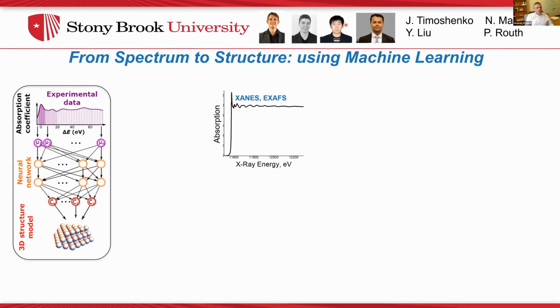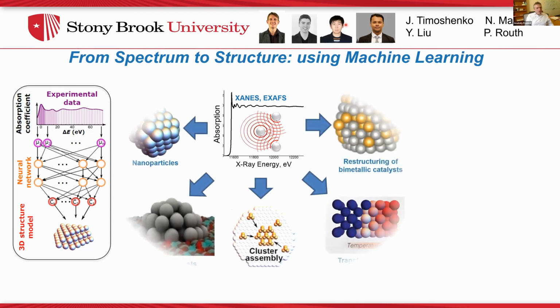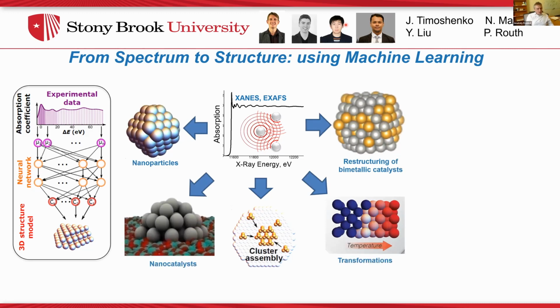But before that, I wanted to show to you that this approach is quite universal. And once we understood how to apply it to nanoparticles, we expanded it to other nanostructure systems that have the same potential. For example, from monometallic, we went to bimetallic nanoparticles and learned about their restructuring by extracting coordination numbers directly from the XANES. And in doing so, we were able to find an alternative to EXAFS, which is the